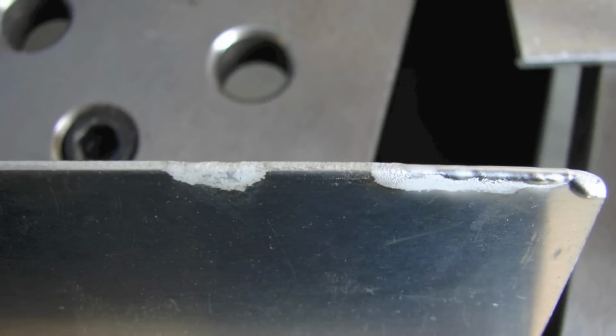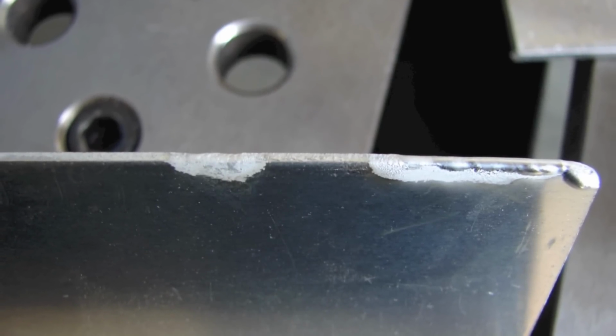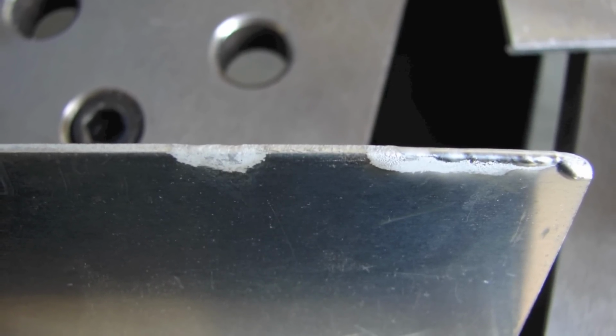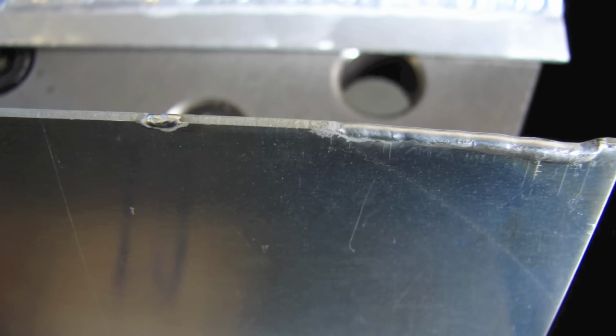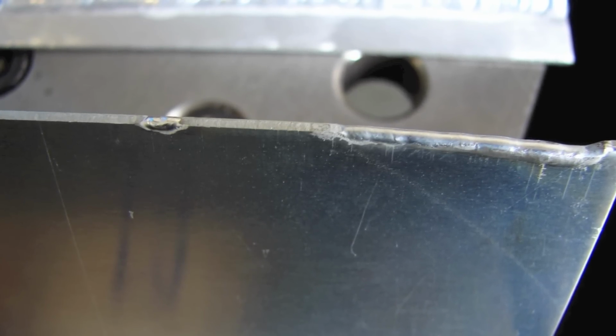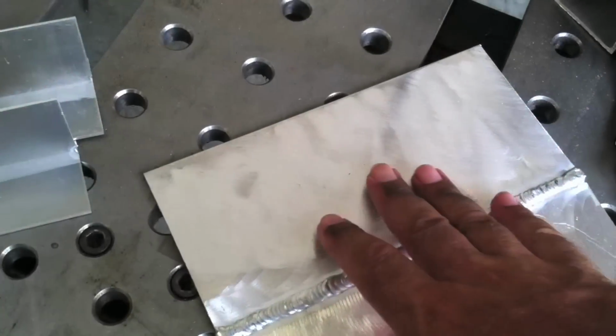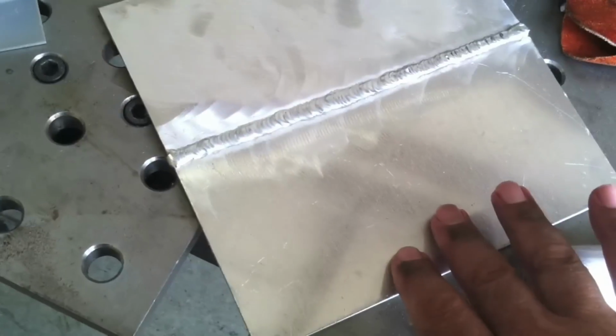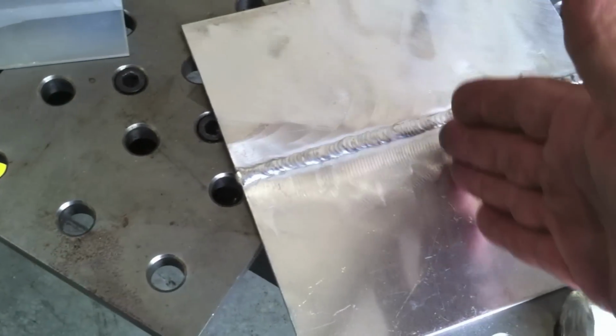All right, here's the aluminum. This is the Everlast run. Everlast actually fared better on the low end on aluminum. Was able to control beads better. This is the Miller. Got a little hot. You can see it nipped it real good where I started. And this is the Everlast. Was able to run a really low amperage bead on the edge of a piece of 16 gauge aluminum. So, you know, one's better in one area, one's better in another. That's not very surprising either. That's generally the way things are.